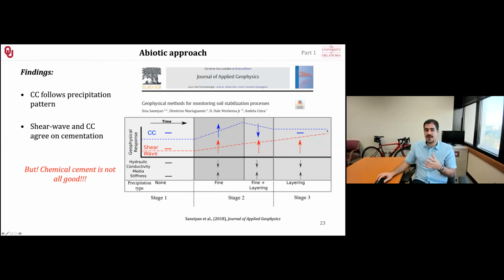This equilibrium is very beneficial, because not only does it tell you to stop, if you have this geophysical complex conductivity method installed at a site permanently and actively monitoring the signal, if this goes down, we know something is wrong, right? So meaning that the site needs maintenance, and we have to go out and inject more material and stabilize the soil. So that actually is really good to know if anything wrong has happened to the site over time or not. For instance, if acid rain happened and washed away calcite or not.